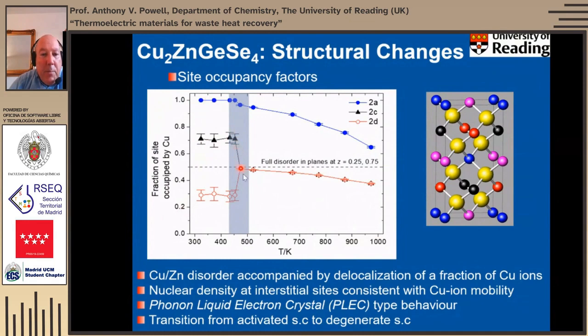But when we heat it up, it appears to get to an order-disorder transition where these copper and zinc cations become fully disordered. So that would be this dotted line here. This would be 0.5 site occupancy factors in each. But at the same time, the actual total occupancy of that site falls away. And also, the occupancy of this site that was fully occupied by copper starts to fall off. So what we find is that the copper-zinc disorder is accompanied by a delocalization of a fraction of the copper ions. And in fact, by the time we get up to our highest temperature of 973 Kelvin, we find that the crystallographic formula involves about a 30% deficiency of copper within that formula.